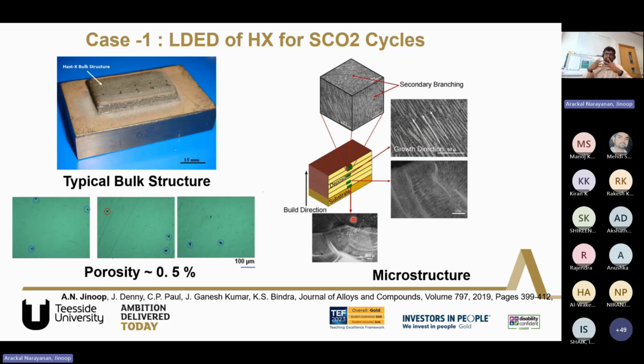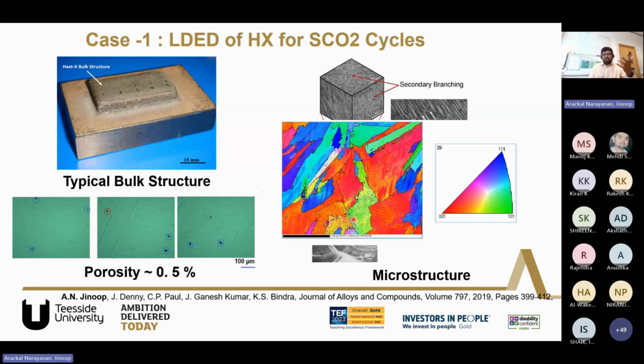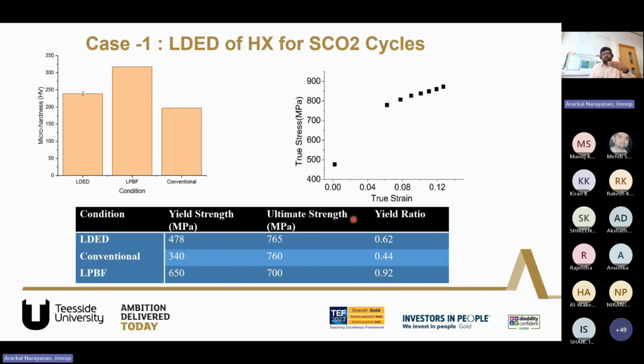We could also see variation in the grain size as we move from the bottom to the top layer, basically because of the variation in the cooling rates, because of the heat transfer mechanism that is happening. And then we did EBSD. We could observe preferred grain growth in the 100 plane, observed typically for nickel-based alloys.